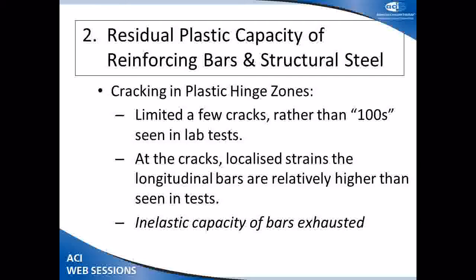Now, from laboratory work that goes back before even we were students, you'd say under multiple inelastic cycles, you'd get yield penetration, bond failure along the bars, anything from 2 to 4 bar diameters either side of the crack. This is partly due to the loading scheme that most laboratories have used over the years, which is to progressively deform your column or your beam more and more and more. This has led, we think, to progressive bond breakdown and a reasonable length of bar either side of a crack